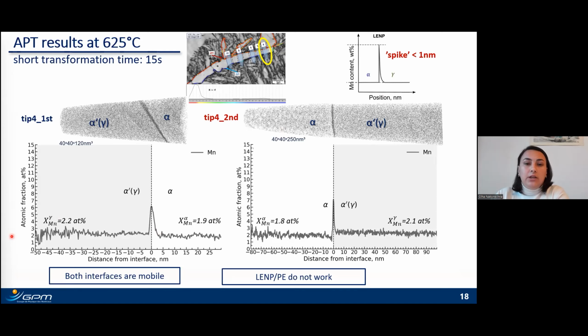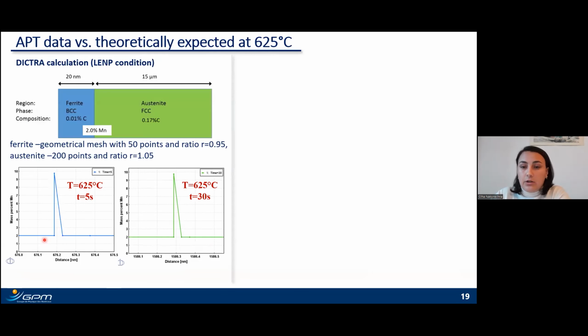So it is already a strong argument to say that the experimentally observed manganese peak cannot be treated as an LENP spike. But to have an additional argument, we compare the experimentally measured data with the calculation using the DICTRA model of Thermo-Calc software.